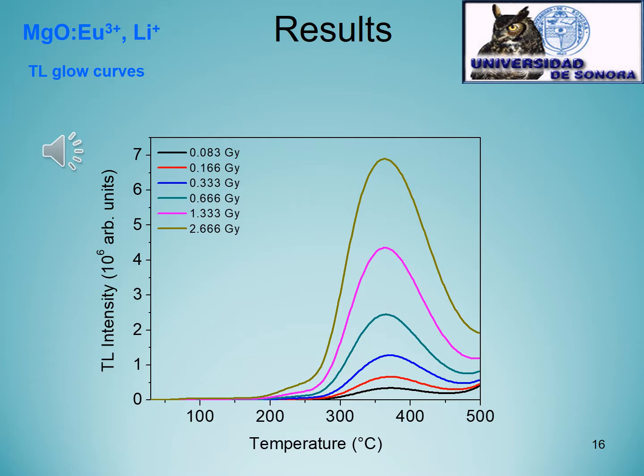We couldn't observe any saturation evidence on the interval studied, and this is kind of a broad peak. We can observe that as the dose is increased, the position of the peak remains, which is characteristic of a first order kinetics for the TL processes.